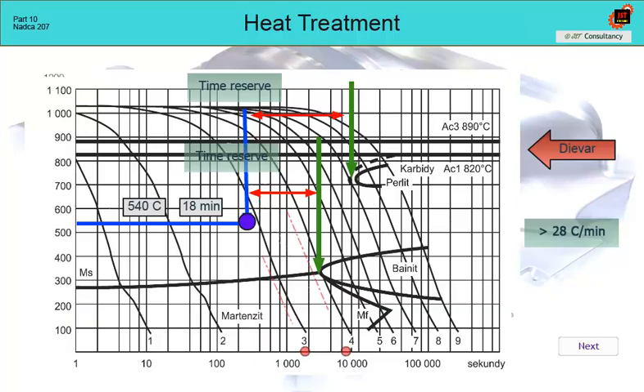Even if Dievar did not have ideal thermal fatigue resistance, it is already clear from these curves that the safety of hardening of dies made of this material, in terms of the resulting structure, is much higher than that of the H11 material. This reduced risk can be used even if we do not have a vacuum quenching furnace with sufficient cooling speed or gas overpressure.